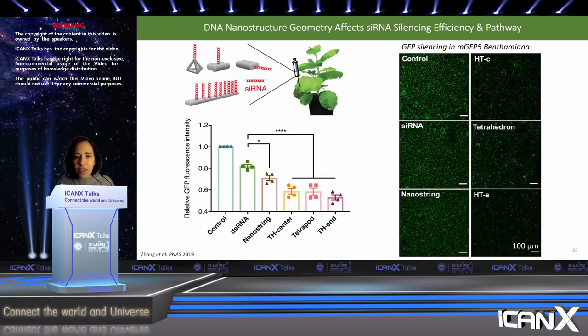Now, because these nanostructures have these loci onto which we can attach functional cargoes such as siRNA, we decided to next test if these nanostructures could deliver functional cargo to plants. So the assay that we're doing here is tethering small interfering RNA to our nanostructures, infiltrating them into our GFP plants, and seeing if we knock down expression of GFP. As you can see here, with these different nanostructures post-treatment to these Nicotiana benthamiana leaves, we see a decrease in fluorescence intensity, suggesting a higher degree of silencing, especially with these three constructs, which matches the level to which they internalize in these leaves. We can, again, validate this at the molecular level by digesting the plant tissue,